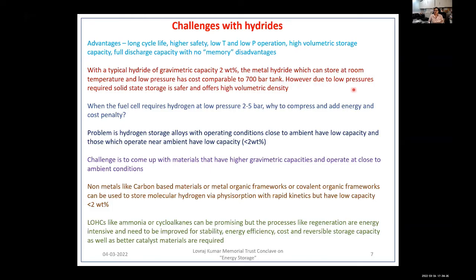Now, due to the lower operation pressure, we can still get a higher volumetric density, because the volumetric density of metal hydrides is far ahead of that of a compressed hydrogen tank. At the same time, we are operating at a lower pressure. So why should we go for compressed state storage? Although it has benefits, my later speaker will talk about it. But when you want to couple that storage system with a fuel cell whose inlet pressure will be 2 to 5 bar, why put extra energy and cost into compressing it to such high pressures? We can use such storage tanks and still operate at a reasonable performance.